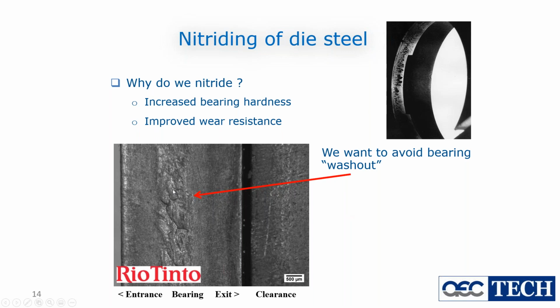This is looking at that surface with higher magnification. You can see that the beginning of the bearing and the end of the bearing are better than the middle. The middle is where you have that transition zone. And then at the end of the bearing, you have just the material sliding over it, which is only abrasive, no adhesive.